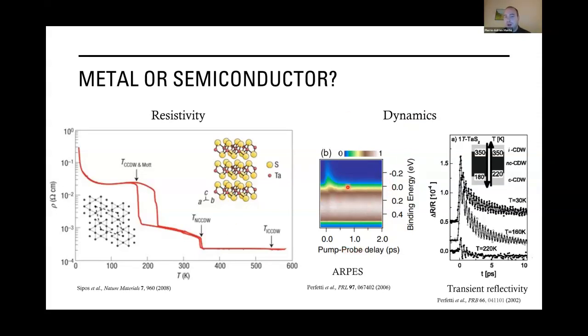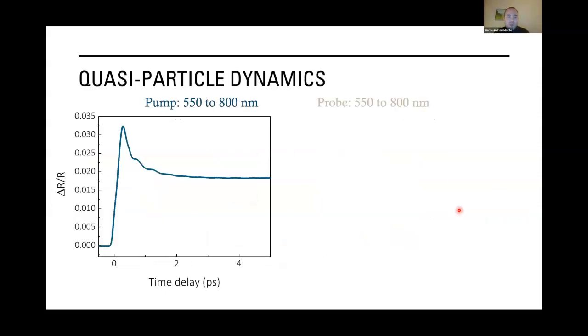On the other hand, if we look at the ARPES data, or transient reflectivity, on a short time scale, the decay can be pretty well modeled with a two-temperature model, where first we drop energy in the electronic system, and the energy is going to go into the lattice through electron-phonon scattering. We performed a pump probe experiment with a wide range of pump and probe wavelengths, using single wavelengths or white light continuum. On the early time scale, we can model our dynamic quite well with a two-temperature model, where we first excite the electrons and they decay exponentially by giving their energy to the lattice. On the longer time scale, heat will dissipate through diffusion.